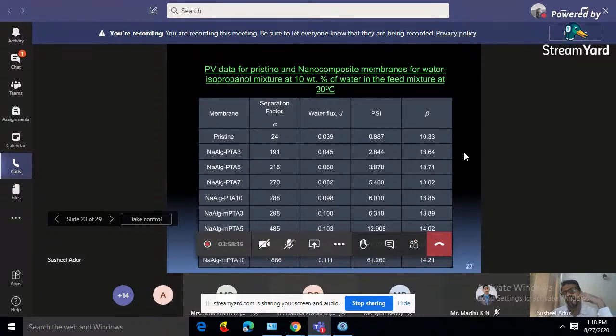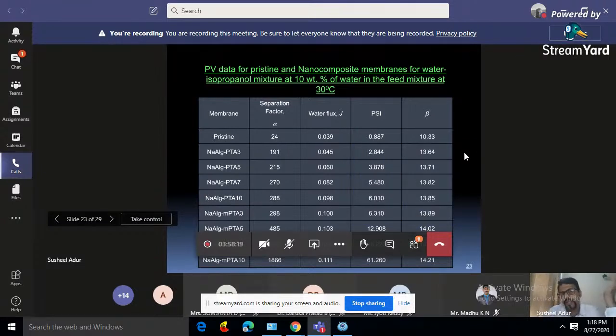Water isopropanol, as I told, forms azeotrope at 12.5% weight of water. But for water ethanol, it forms only at 4%. Then you can imagine, at 4%, it becomes extremely difficult for any later compositions. If I go for 10 weight%, 20 weight% of water, it becomes extremely difficult to separate water from water ethanol. So when I use the pristine membrane for 10 weight% of water, separation factor is very less, 24, and flux is also very less, 0.039.